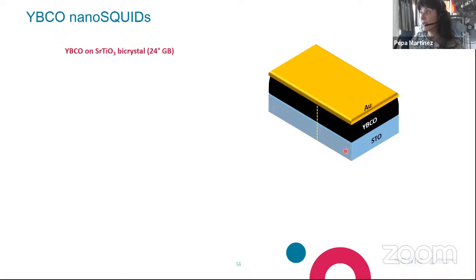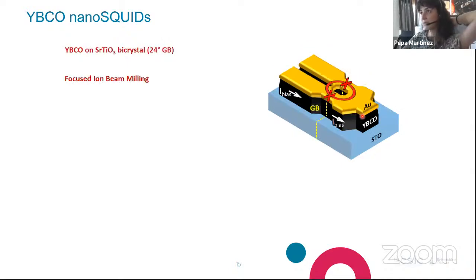We start with a bicrystal substrate of STO, in which we have a grain boundary. Then a layer of YBCO is epitaxially grown on top of it. In this way, the grain boundary is transferred to the YBCO layer. And finally, we cover this substrate with a thin layer of gold. I will tell you later if you like why this gold is important. We later pattern our nanoSQUIDs by using focused ion beam milling, leading to the formation of a nanoloop interrupted by the two Josephson junctions, as you see here.